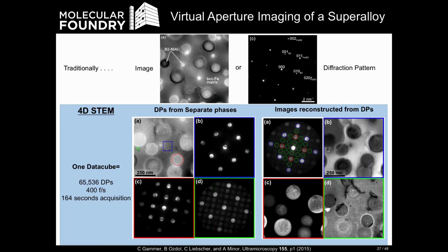On the left-hand side, in the upper left, I'm showing the virtual image. This is from a paper that Christoph Gammer, a former NCEM postdoc, wrote. You can see in the green triangle, the blue square, and the red circle, the different virtual diffraction patterns. These are formed by simply summing up all of the diffraction patterns underneath those pixels. You can see this is a fingerprint of all of the different phases here. We can tell the difference between the different local ordering based only on the intensity or absence of the various diffraction spots. Alternatively, you can approach the data from the diffraction side.